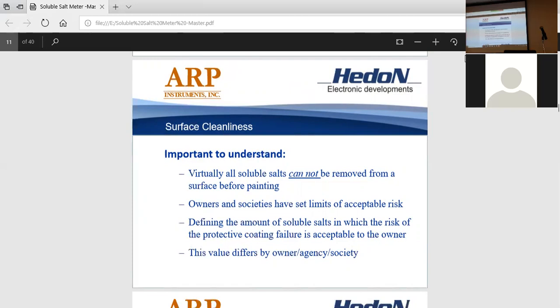There can be, yeah, at the surface, it could break down the coating system. Poor application and too thin. Yes, too thin. So if we're doing an inspection, contamination or poor application would probably be at the top of the list. If you see a large area of contamination, not too many blisters, that's usually an indication of poor surface prep and or not enough paint per spec. Or they missed the overcoat window. There are so many things you've got to know. You've got to know that behind stiffeners is where they typically miss areas, and on the edges of those stiffeners where they don't stripe coat. All those areas can compromise a coating and form blisters like you're describing.